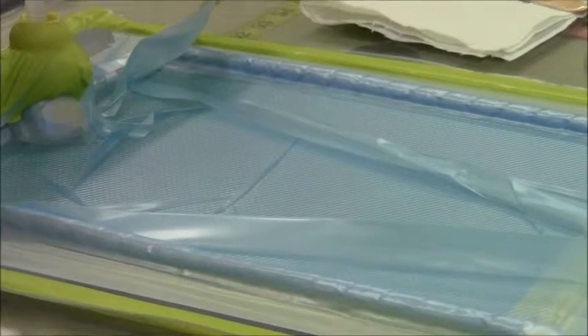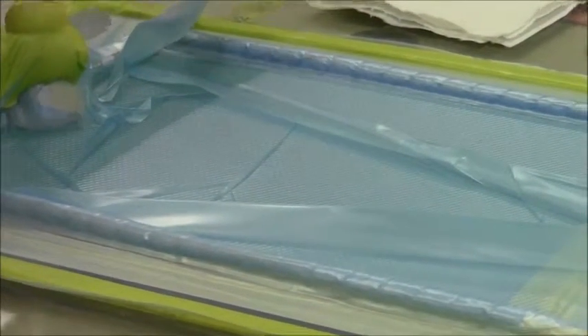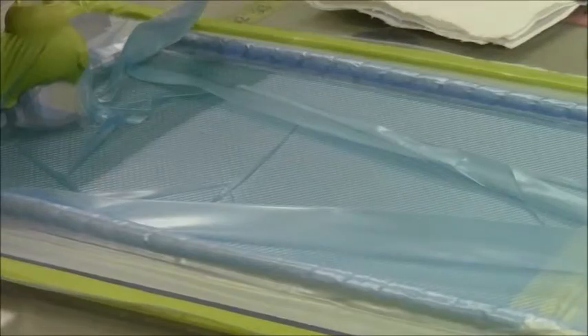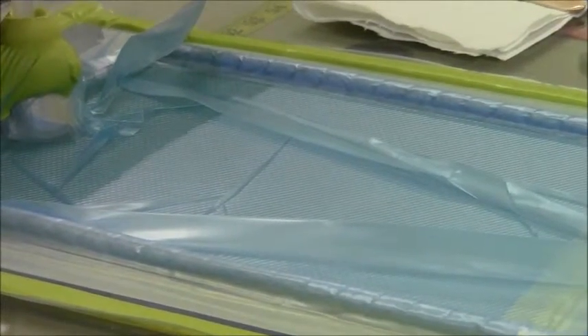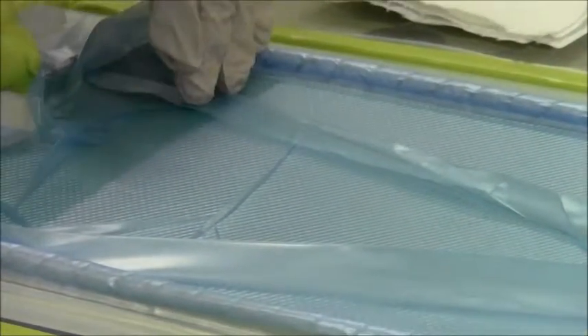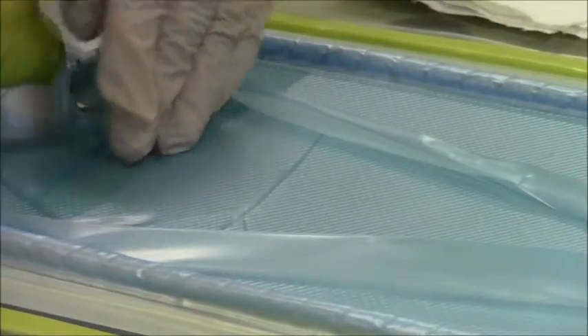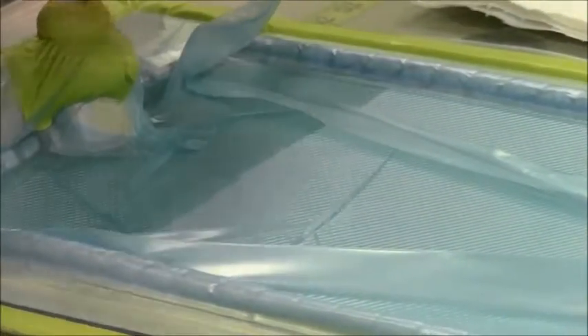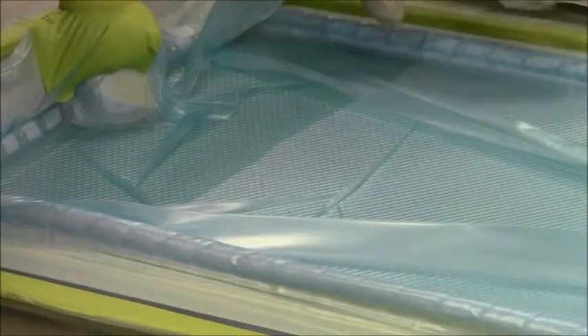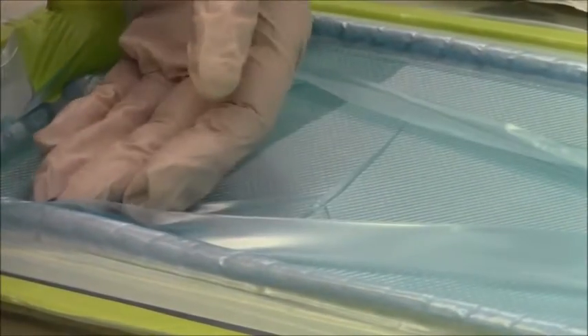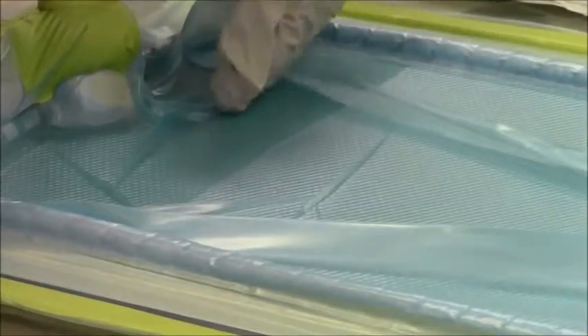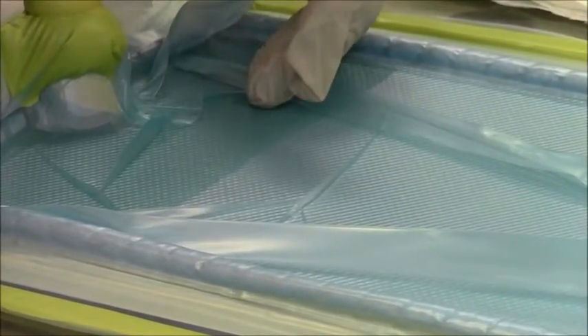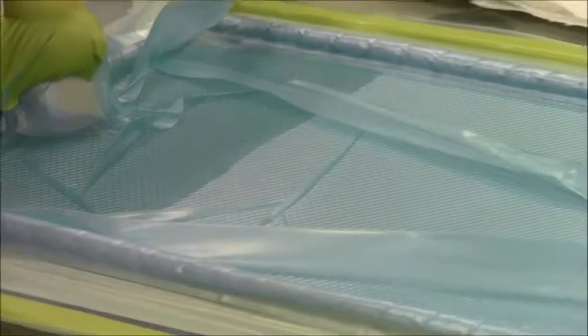You notice how the resin jumped out and I'm slowing it down here with this MTI valve. As you can see, I have a very consistent, smooth, straight resin flow front that tells me that I don't have any leaks anywhere and that the MTI hose is doing its job. The MTI hose will allow resin to contact it, but won't allow any resin to enter into it. This minimizes the amount of resin that we actually use in the infusion and reduces your waste.